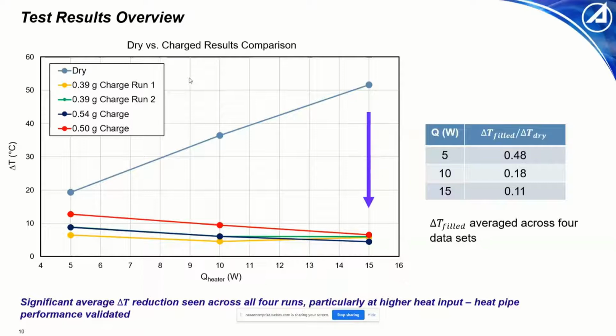You can see at all heat input values, we demonstrate significant improvement when we're using a filled heat pipe, but particularly at high heat inputs, 15 watts, we see almost a 90% drop in the delta T. So a significant average delta T reduction seen across all 4 runs, and this validated our heat pipe performance. We can conclude that additive manufacturing is viable, and it does create a heat pipe which can be sealed and can operate in heat pipe orientation.